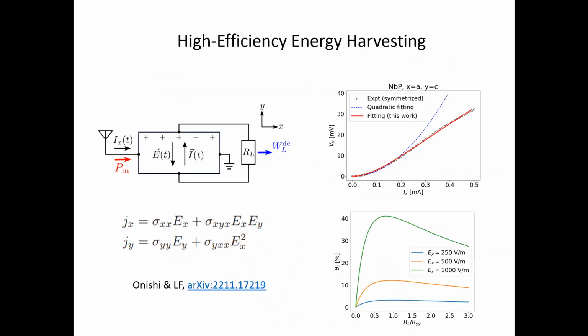Let me just briefly mention that we also considered recently, with my student Yugo Onishi, the possibility of harvesting energy from the AC electric field of electromagnetic radiation using this nonlinear Hall effect. Because of the Hall response, the Hall current is perpendicular to the applied electric field, so by itself the Hall effect does not create dissipation. We find that if the nonlinear Hall angle is large, then the energy conversion efficiency from AC to DC can reach the order of a few tens of percent. So this could be useful for harvesting a small amount of energy.